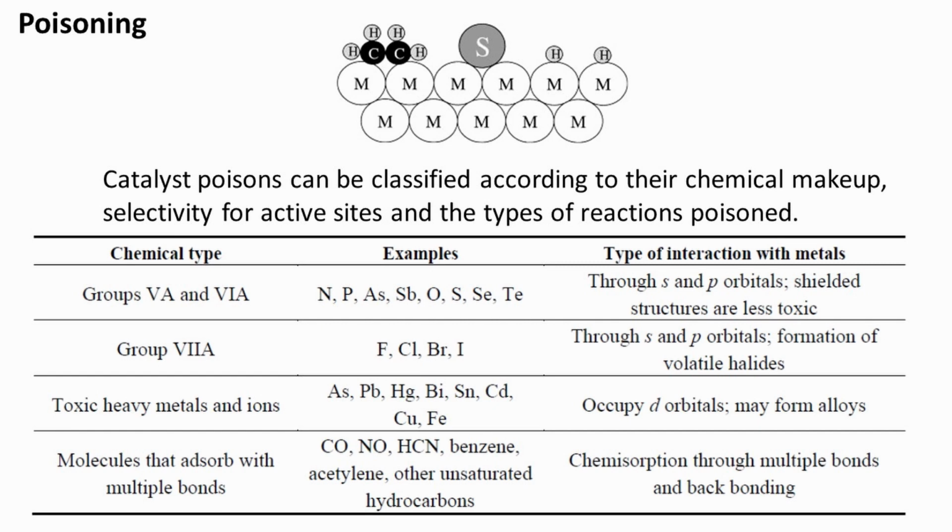To begin with, a strongly adsorbed atom of sulfur physically blocks three or four top sites of the metal surface. Second, by virtue of its strong chemical bond, it electronically modifies its nearest neighbor metal atoms and possibly its next nearest neighbor atoms, thereby modifying their ability to adsorb or dissociate reactant molecules, in this case hydrogen and ethylene molecules.